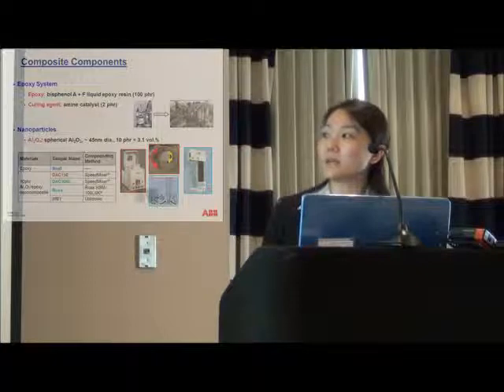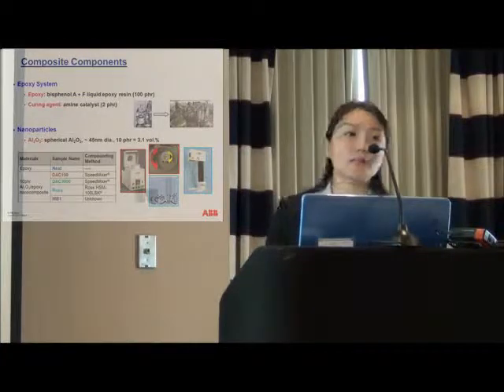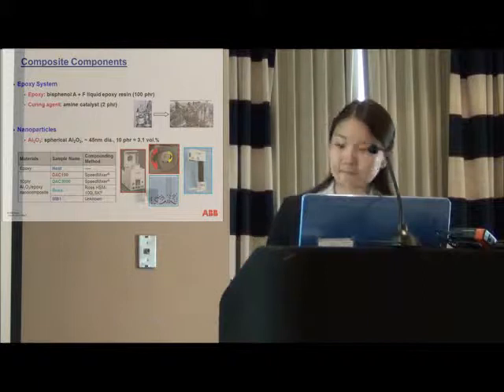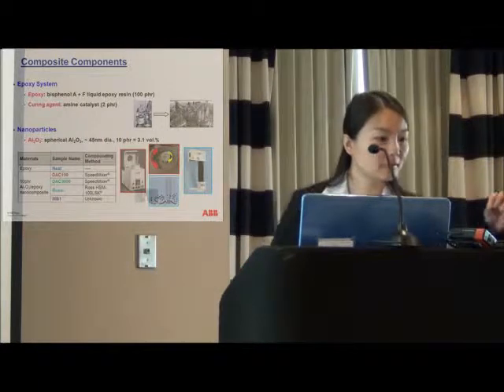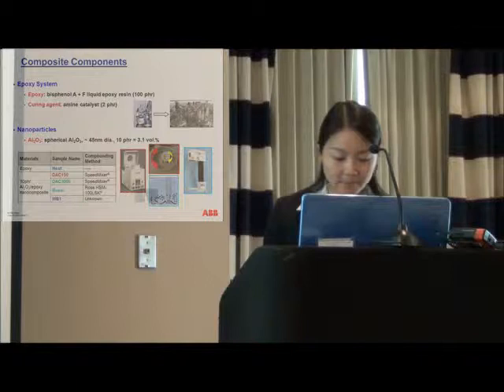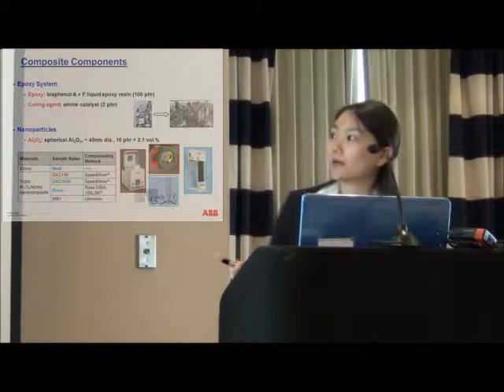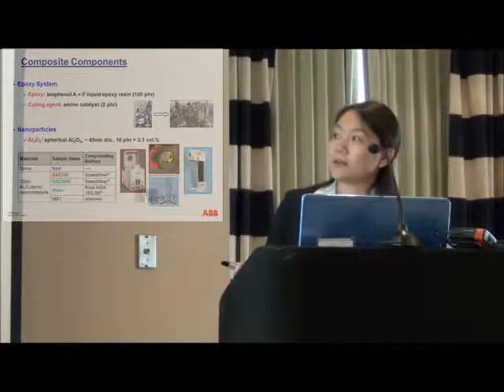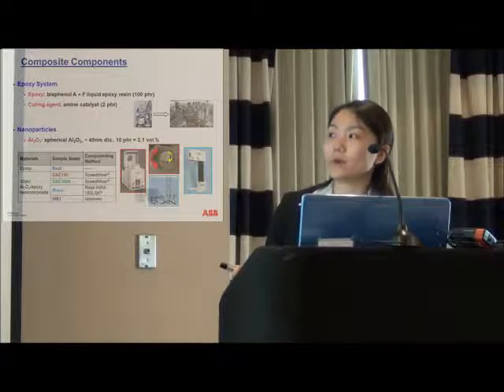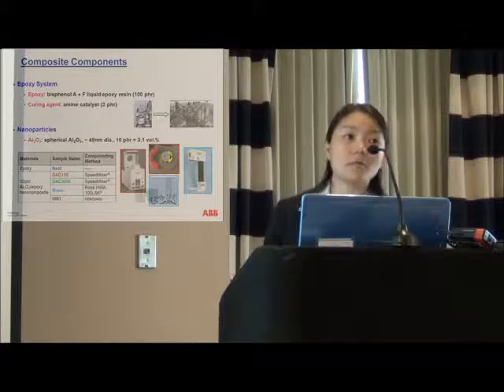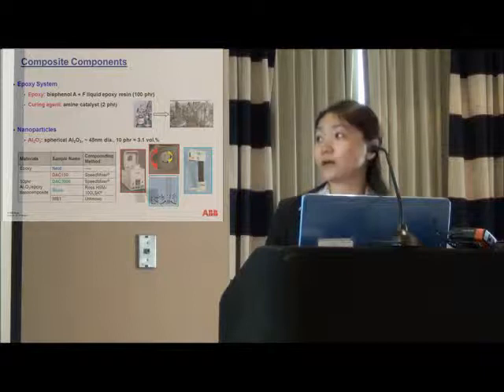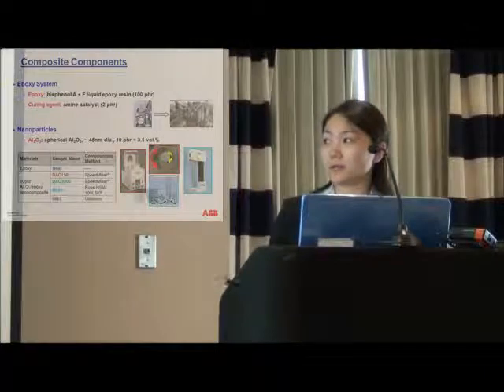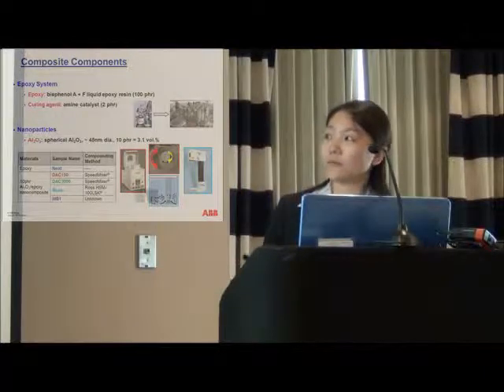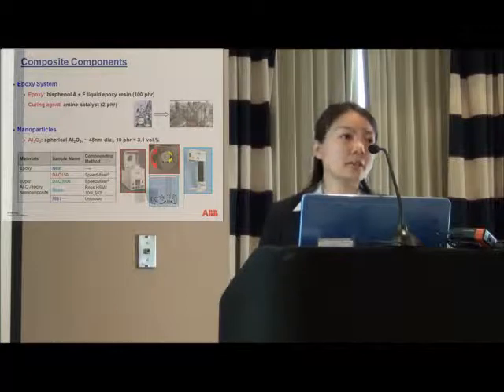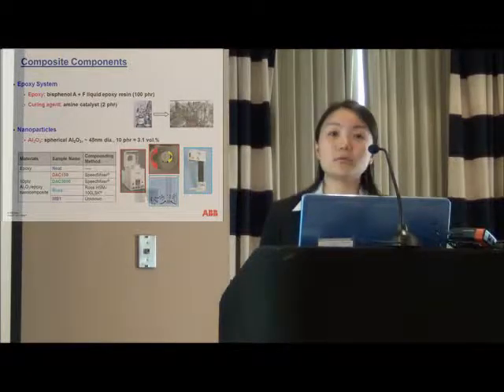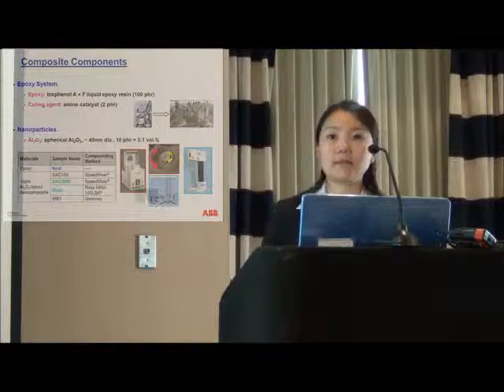The principle of this machine is you put the sample in a cup, and it rotates in one direction while the main stage rotates in the opposite direction, with an angle between the cup and the main stage. This kind of movement provides very high shear stress to disperse the particles, and you don't need to use any propeller, so it's very clean and neat.